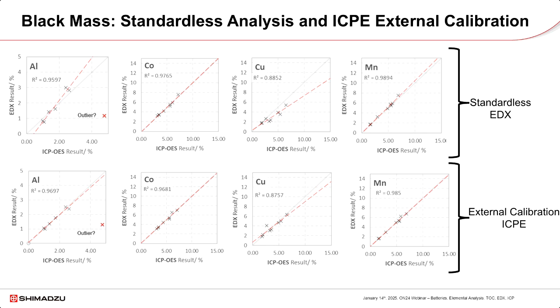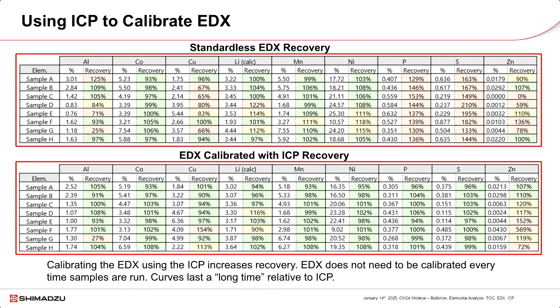Note the remarkable improvement in correlation between the EDX and the ICP data, especially in the range of element concentrations being measured. In other words, the red dotted line has a high degree of overlap with the solid gray line, especially in the range of element concentrations being measured. Similar to the graphs previously shown, the numerical data also indicates that calibrating the EDX with the ICP results in an increased degree of analytical accuracy.